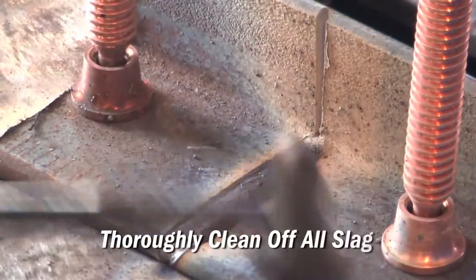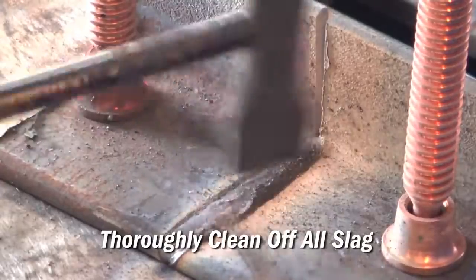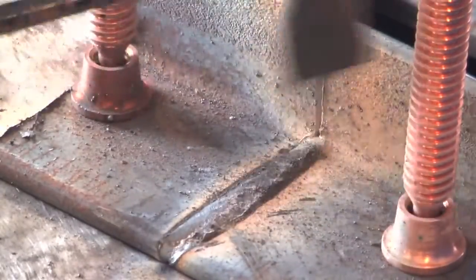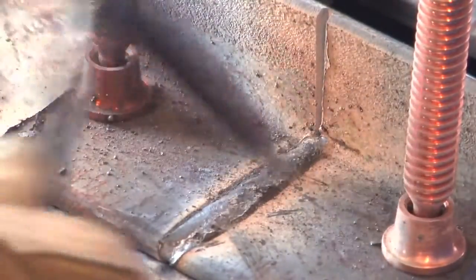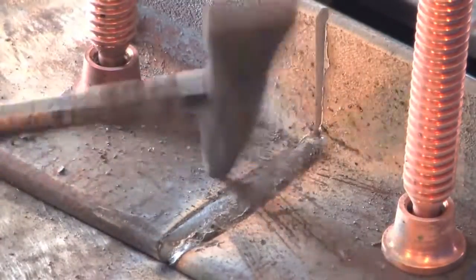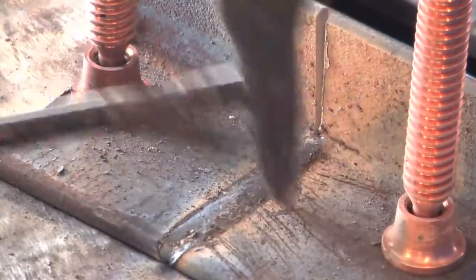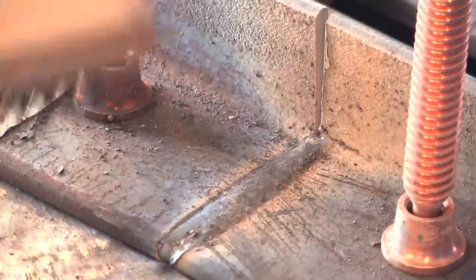With flux core welding, you're going to have slag that's left behind when you're done with your weld. Different wire types produce slag with different properties, but either way, all of it must be chipped, scraped, and brushed off completely before you make a second pass or make multiple passes on thicker material.